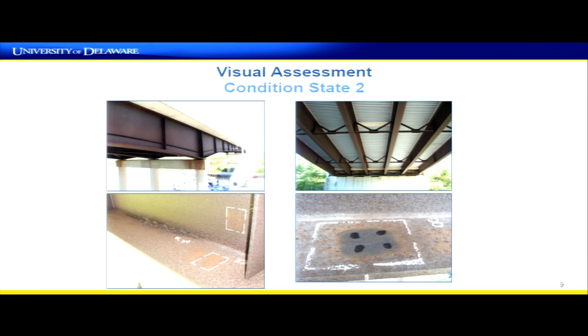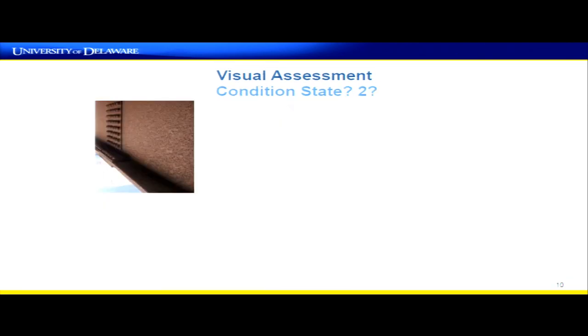This example on the right I chose because, again, this is obviously pitting, but when you're looking at this photo taken from the abutment, the weathering steel, you can't see a problem here. So this I just want to highlight from an inspection standpoint. You really do need to get a closer view than just standing at the abutment and looking from there. So those are examples that fall very neatly into condition state 2.